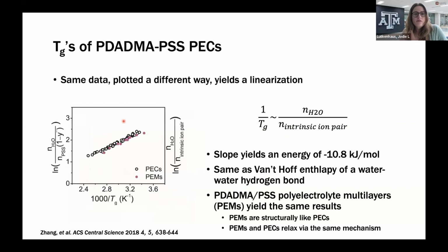Now, what's even more curious, if we take that same data and plot it just a different way, we retrieve a linear relationship, no adjustable parameters, but it's linear. So if we take the natural log of water per intrinsic ion pair versus 1/Tg, it's linear. And the slope gives you an energy of 10.8 kilojoules per mole, which is similar to the van 't Hoff enthalpy for a hydrogen bond. So this is another clue that there's some sort of interaction of water happening at the intrinsic ion pair to allow the polyelectrolyte chains to slide past one another and go through this glass transition and more macroscopic relaxation.